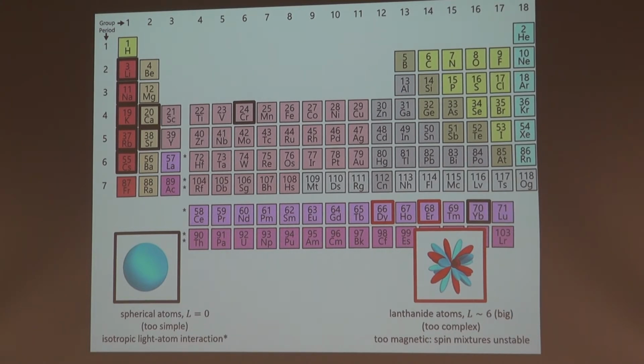So it's for that reason, in particular, the fermions that we have, let's say lithium and potassium, they turn out to have really weak spin-orbit coupling in the excited state, so it's really hard to create long-lived spin-orbit coupling in these gases. Alternately, we have these lanthanide atoms that have also been made quantum degenerate, and they are very anisotropic. They have a ton of angular momentum in the ground state, so no problem creating strong spin-orbit coupling, even for light that is very far from the atomic resonance.